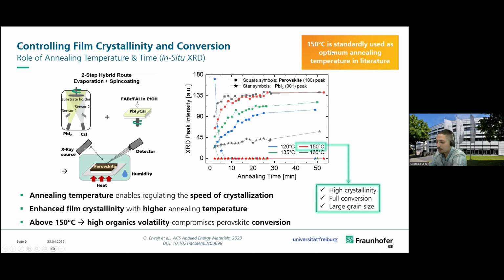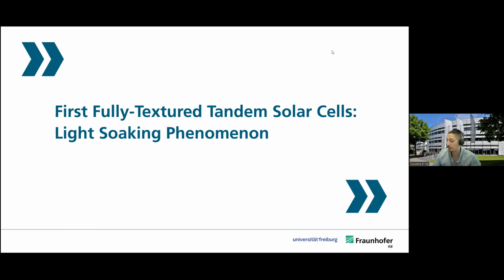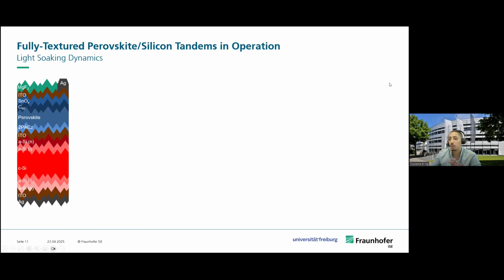So now that we have seen the impact of different process parameters on the perovskite film quality with the hybrid method, what happens if we put this film in a fully textured tandem? This will be the second part. Here we directly placed the perovskite film in a PIN perovskite top cell where we had 2PACz and C60 as charge transport materials, and we had the silicon heterojunction as a silicon subcell. When we first measured these devices, we observed a large hysteresis between forward and reverse JV curves, and we observed a severe S shape.